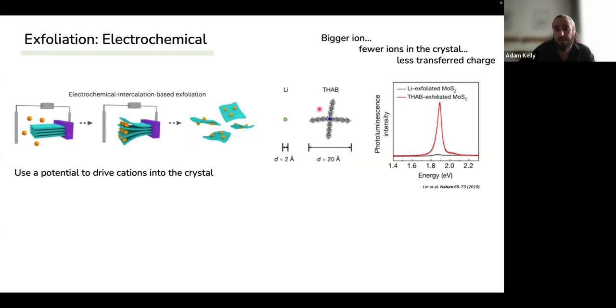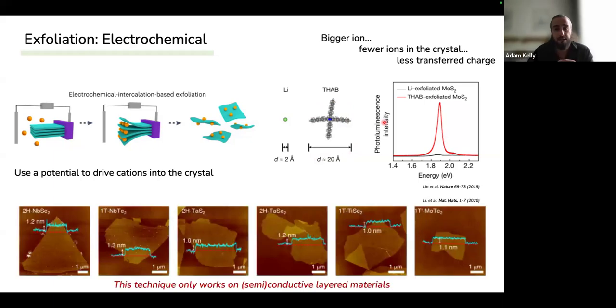And when you use this ion here instead of lithium, what you find is you retain the semiconducting character, as represented here by the photoluminescence, which only occurs in monolayer semiconducting MoS2. Now, this technique, because we need to apply a potential to the crystal, only works on semiconducting or conducting layered materials. So we're restricted here: the crystal needs to be conductive. But what the difference is, the nanosheets or